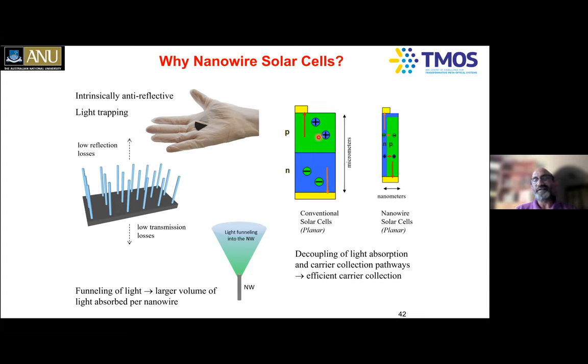But in the case of nanowires, you can make the nanowire as long as you want to absorb all the sunlight, and then you make the PN junction in the core-shell structure, for example, with a P-type core and N-type shell, and thereby the carriers can be collected very efficiently. And now you're, for the first time, decoupling light absorption pathways and carrier collection pathways. But also these nanowire structures have low reflection losses, so you don't need to put any anti-reflection coatings or anything. Also, because of the high refractive index of these nanowires, they act like light funnels.